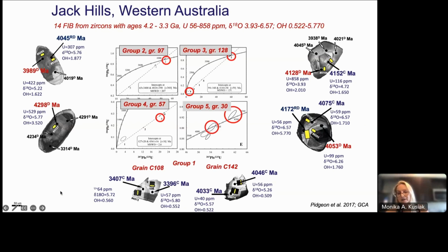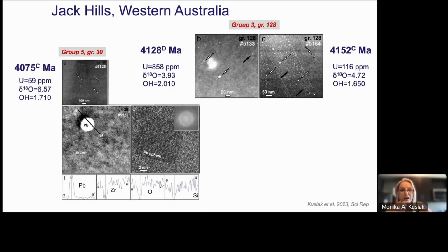And this was a very careful study, and I have to tell you that we found lead nanospheres in Jack Hills zircons with no correlation, or no possible correlation, to either uranium content, oxygen content, or OH content. We found them in concordant, discordant, and reversely discordant data. The only thing is that we didn't find them in grains which were younger, the 3.3 billion year old grains, and we didn't find them in grains from group 1, the most pristine and very nice grains.